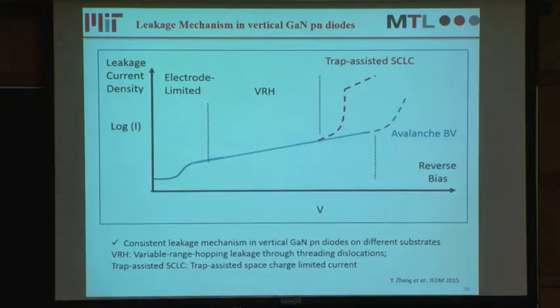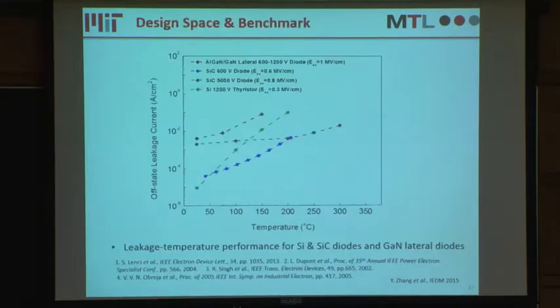So this is the leakage mechanism of the vertical gallium nitride power devices. And after we have all this well-calibrated simulation models and experimental data, we're able to benchmark the design space of the leakage current in gallium nitride vertical devices with some other devices, like the gallium nitride lateral devices and the silicon carbide silicon devices.